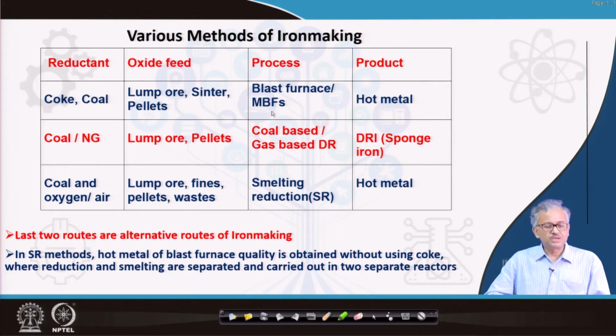These are the processes I am talking about, and in this case the reductants are mostly coal and coke. Coal sometimes comes in the form of pulverized coal injection. You can also use charcoal for a mini blast furnace or charcoal blast furnace. So these are the reductants, and oxide feeds are basically the lumpy ore, sinter, and pellets. And what is the product? You get hot metal, which is saturated with carbon, and it also has impurities like silicon, manganese, phosphorus, sulfur. Okay, this is a conventional method.